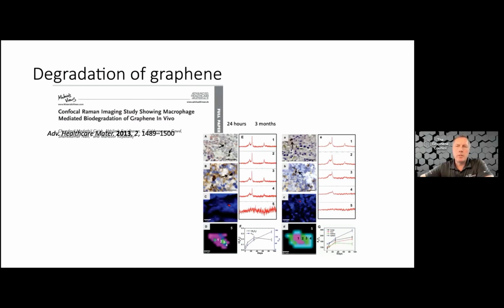And well, that also speaks to another question, about the transparency of the material. A monolayer, a single atomic layer of sp2 bonded carbon, is, I believe, 97.7% transparent. Right? It's 2.3% non-transparent. Yeah, it's very slightly gray. So you can see it with the bare eye. You see graphene, with respect to no graphene on the bandage, as a small, smoky contrast, but it's very, very transparent indeed.